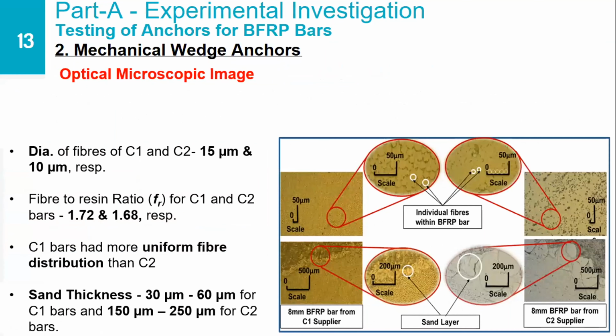We also studied the microscopic image of the 2 types of FRP bars just to see the fabrication procedure that has been applied to these bars. We noticed that the bars provided by the C1 and C2 suppliers had fiber diameters of 15 micrometer and 10 micrometer respectively. The fiber to resin ratios for the two types of bars were 1.72 and 1.68, quite close.